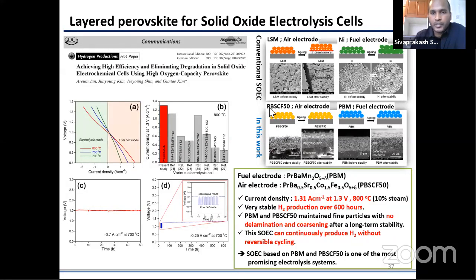But using praseodymium barium strontium cobalt as the air electrode, there is no oxygen buildup in the interface between the electrolyte and the electrode. Even in electrolysis mode, there is no interfacial breakdown, whereas in the LSM material there is a huge breakdown. In the fuel compartment, when we use praseodymium barium manganese oxide as the electrode, even switching from hydrogen to water, there is no structural or volume change. It shows a very stable performance in fuel cell and electrolysis mode.